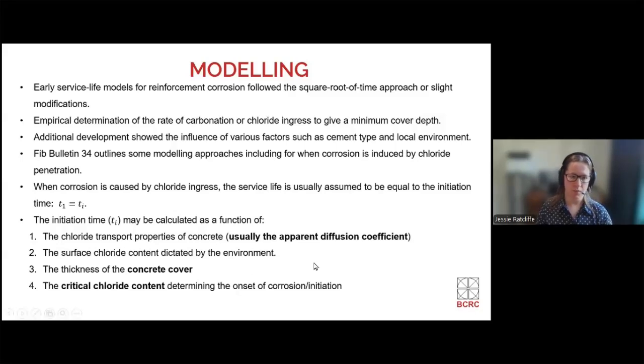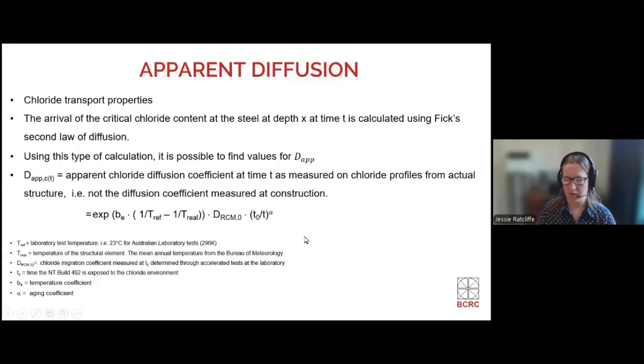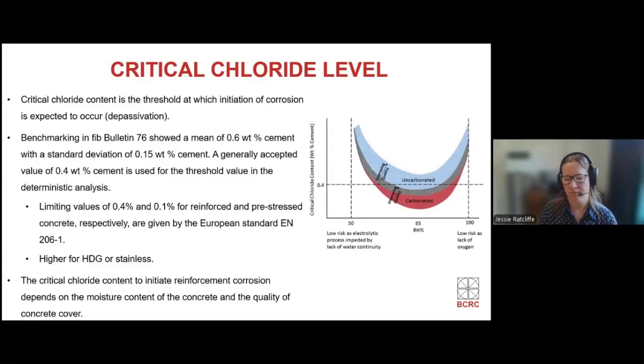Our initiation time, so our start of corrosion, is calculated using the apparent diffusion coefficient, which we'll calculate in a second, our surface chlorides, thickness of concrete cover, which we've already talked about, and the critical chloride content, that 0.4% weight of cement. So our first one is the apparent diffusion coefficient, which is our chloride transport properties. It's the equation there. We'll show it on a graph shortly, which is much easier.